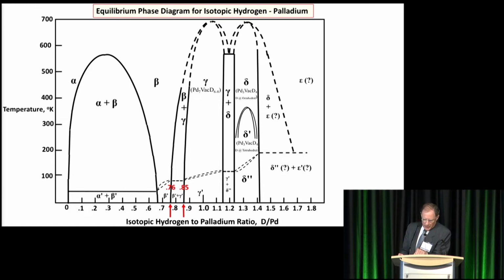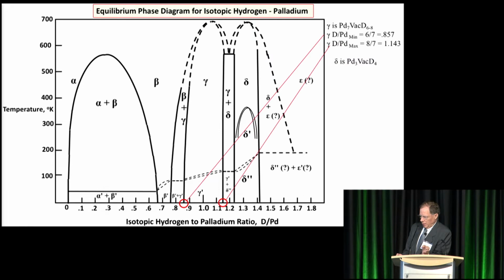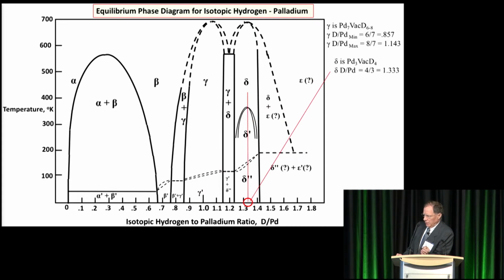For the sake of time, I'm going to skip over some of the detail here as to where those exact boundaries are, but notice that there's the beta phase, which we're all familiar with, the gamma phase, which was the lower vacancy concentration, the Pd7 vacancy D6 to 8, and then the delta phase, which was actually discovered before the gamma phase, which is a Pd3 vacancy D4 and its location. And we already talked about the range for the deuterium to palladium being from 0.86 to 1.1. And the center of the delta phase is at 1.33.